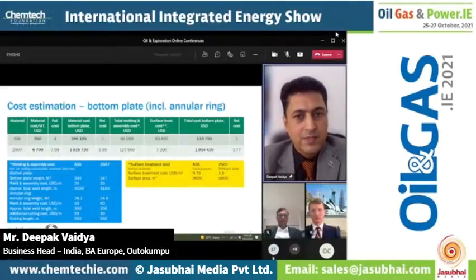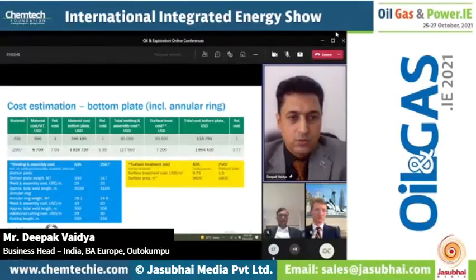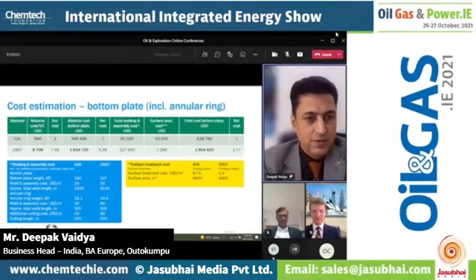Then you go to the welding and assembly cost. Welding for bottom plates on the left side, the weight we have taken is roughly 330 metric tons to 247 tons. Weld and assembly cost we have considered for A36 is around $20, whereas for stainless steel it is a bit high, almost 1.5 times, $30 per meter. And the length will be the same.